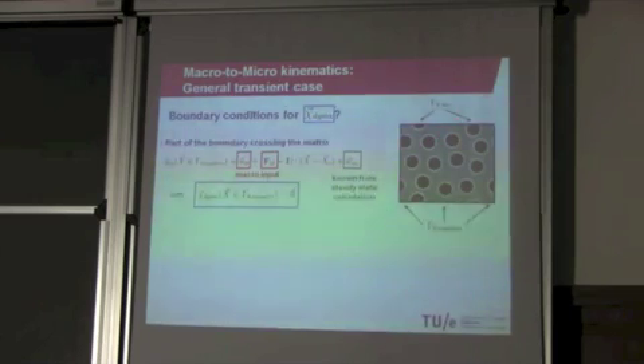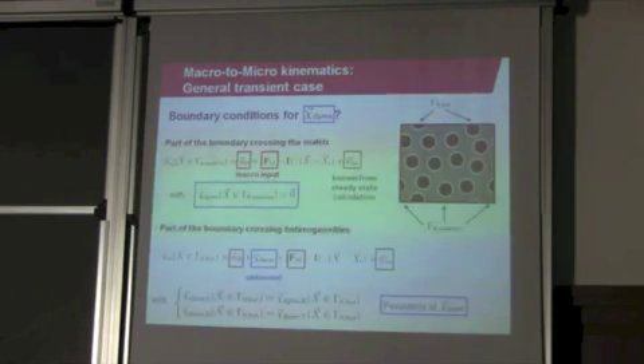So if we consider the matrix, we said that for the matrix, the full separation of scales is still valid, so the matrix can be assumed to be in a quasi-static state. So in that case, we can assume that the dynamic microfluctuation on the matrix, so on the parts of the RVE that is on the matrix, vanishes. And on the parts where we have inclusions, where we here assume that it's geometrically periodic, we then can assume the dynamic microfluctuation also to be periodic. Again, this is an assumption, this is a choice, but it turns out that it works. Okay, now the interesting thing, or probably the most important thing here, is what are actually the scale transition relations that now correspond to this problem.